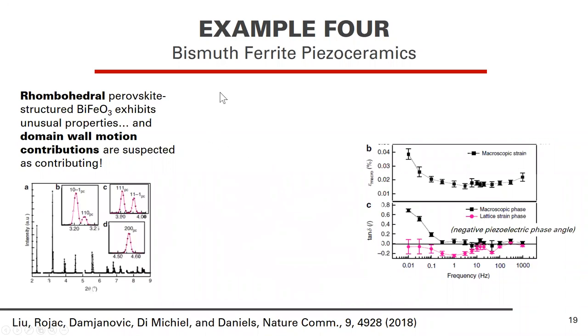Example four is a rhombohedral perovskite structured bismuth ferrite sample. And this is a sample that comes out of Rojac's group, Jožef Stefan Institute. And they worked on this material for quite some time. And one of the interesting physical properties that they observed is that the tan delta, or the piezoelectric phase angle, becomes negative at particular frequencies. And they wanted to understand the different mechanisms contributing to that negative piezoelectric phase angle.